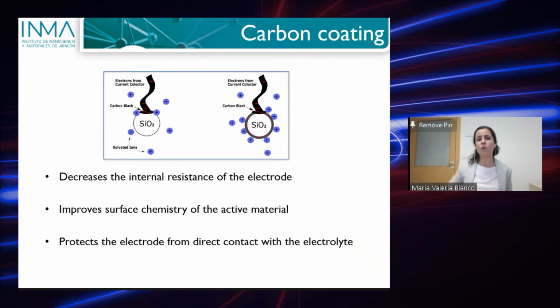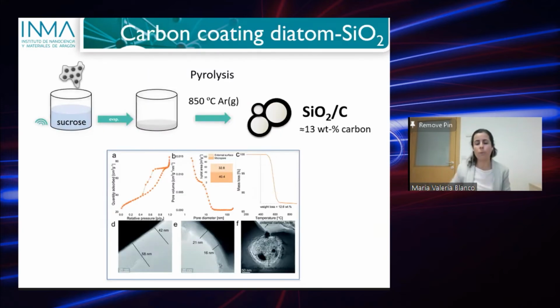So after the milling, we also need to do some coating of the particles with some conductive material. This is because we don't want to have the silica particles in direct contact with the electrolyte, because that will damage the particles. So we need some protective layer to prevent this direct contact with the electrolyte, and also to add some conductive character to the particles, so that we can decrease the internal resistance of the whole anode. For this, we implemented some carbon coating treatment. We played a bit with a lot of parameters. We used different carbon precursors, different temperatures, different percentages of carbon precursor to see which was the optimized way of doing the coating on the particles. And we ended up using sucrose as a carbon precursor.